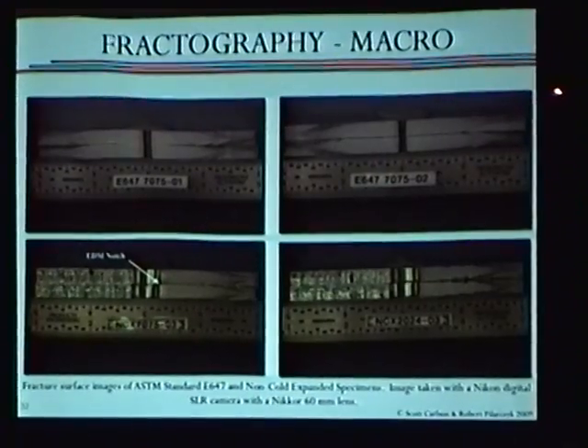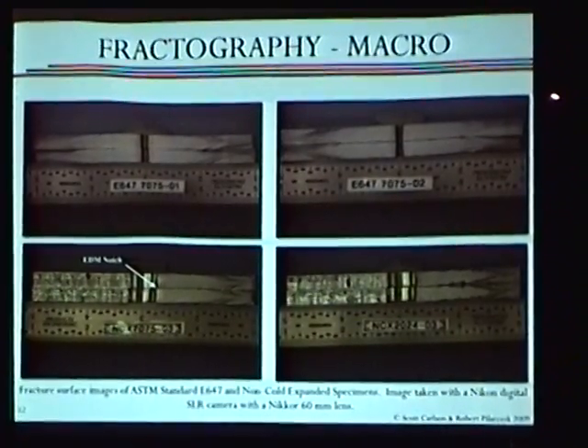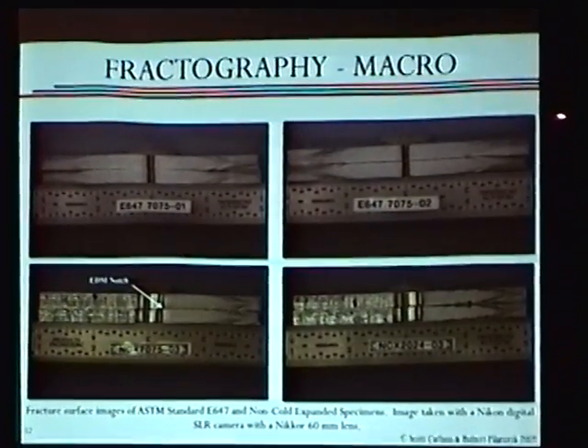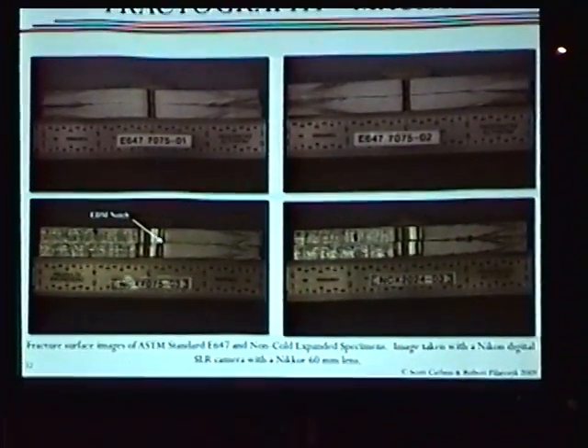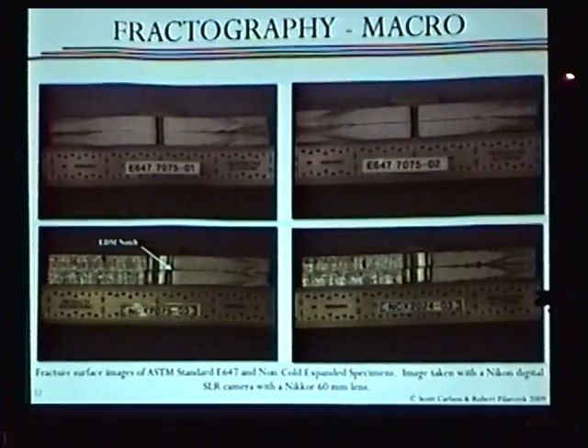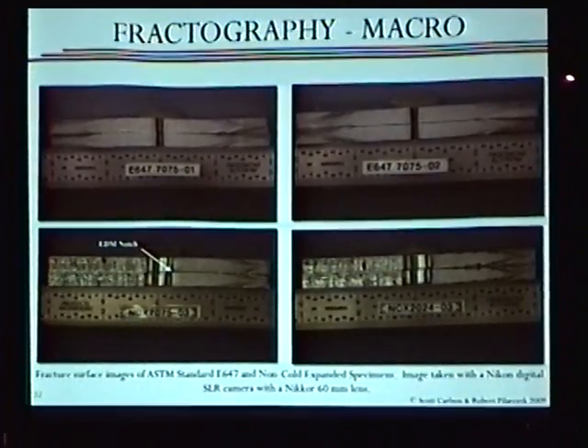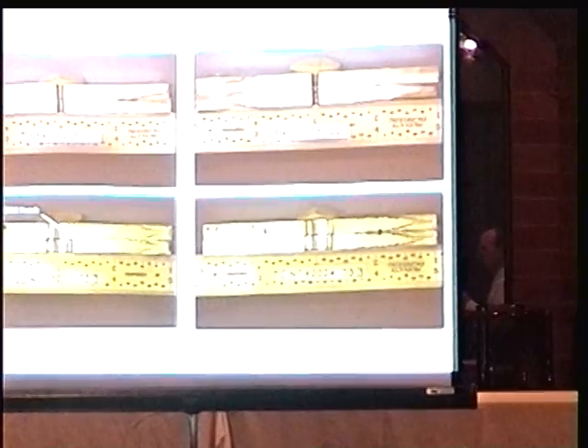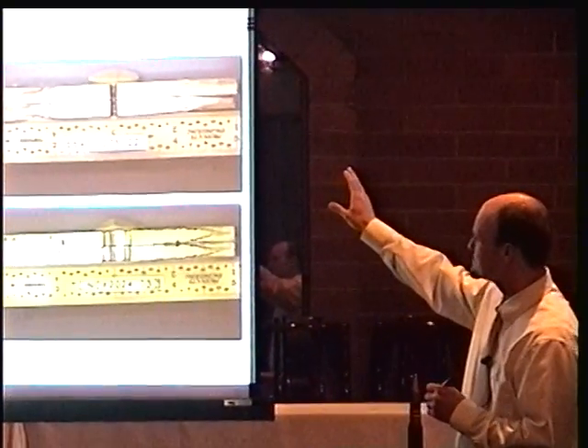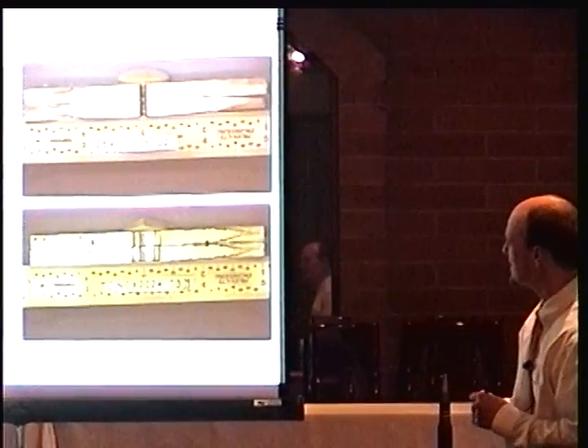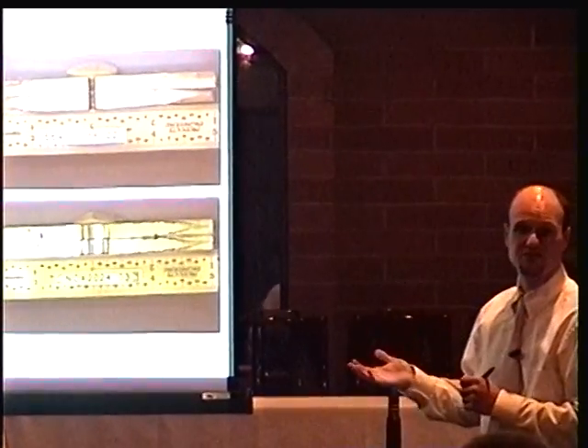Now, we passed around some specimens. I've got a bunch of pictures on here. So really what you're looking at is we've had specimens that cracked, failed. We've broken them apart, and these are the two fracture surfaces. You see in these pictures, those are the two fracture surfaces laying on top of each other, and you're looking at that fracture surface. And there's a couple things that I really want to talk about that I think really affect NDI. The first is I've got just some E647 specimens that we tested, and I've got non-cold work specimens. And the one thing I really want to talk about is the morphology of the fracture surface.